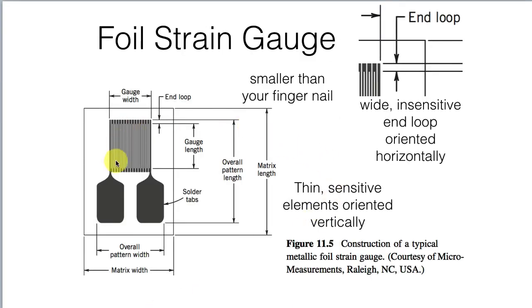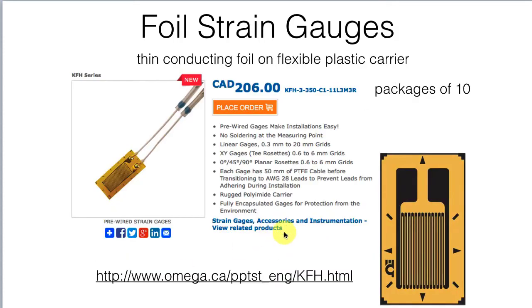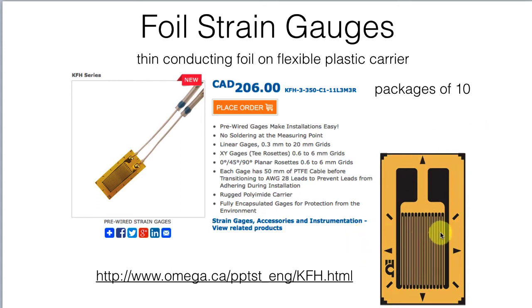This foil strain gauge has many thin resistive elements that are sensitive to stretching in the vertical direction, and because these elements are wide, they're not very sensitive to stretching in the horizontal direction. When buying these gauges, you'll see a plastic carrier with a thin film conductor etched onto it, with alignment lines to help you position it on your workpiece. Soldering pads are provided for wires. High-quality strain gauges from vendors like Omega run around $200 for a package of 10, in a variety of configurations.